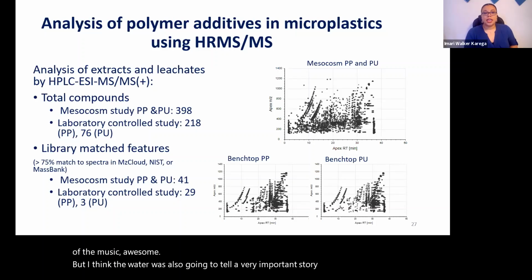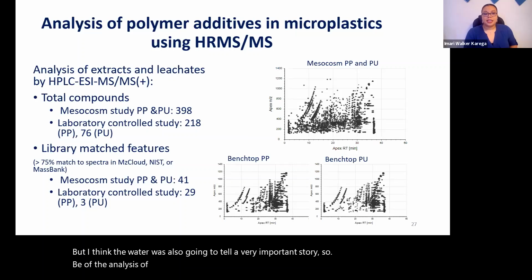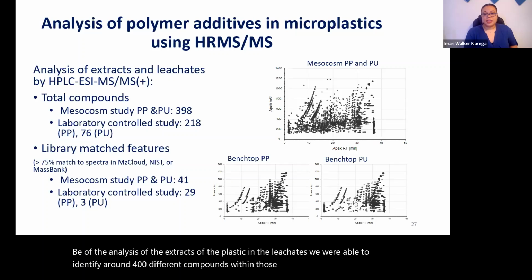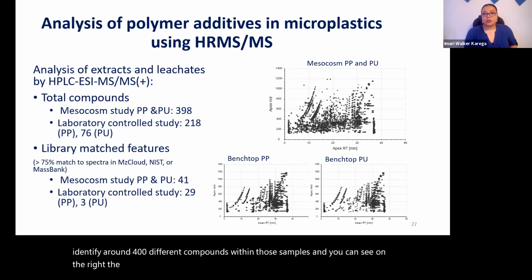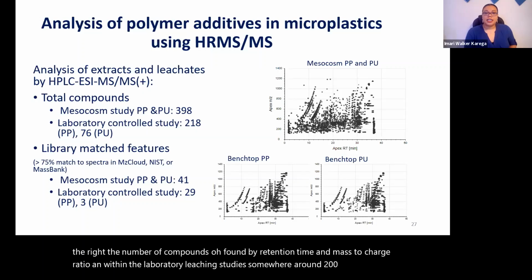So the analysis of the extracts of the plastic and the leachates, we were able to identify around 400 different compounds within those samples. You can see on the right the number of compounds found by retention time and mass to charge ratio. Within the laboratory leaching studies, somewhere around 200 to 300 compounds were identified.